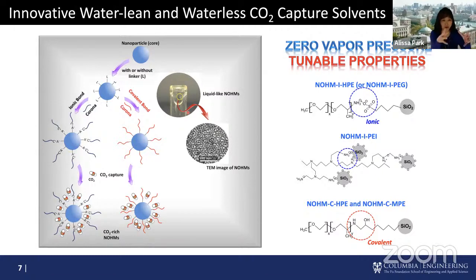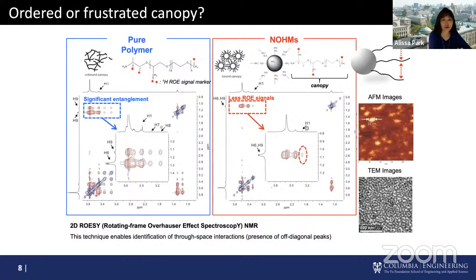Not only that, we will make this material such that the tethered polymer will hopefully have a very different structure. By doing so, we can have not only enthalpy from the amine functional groups, but also an entropic contribution to enhance CO2 capture. So the first generation of these materials was these two examples shown here. These are the NOHMs on the right-hand side, tethered with HPE, and on the left-hand side is just the unbound polymer we started with. What we wanted to see was, by tethering them, do we really change the structure of these materials or polymers present in these liquid systems?